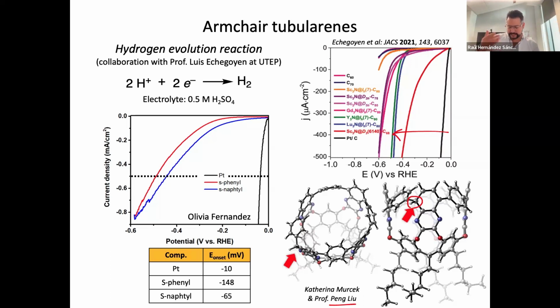There were hints in the literature that you could do this with CPPs. However, asking some of the leading scientists in CPP chemistry, they told us that one of the things that happens is you see a 1,2 shift in the aromatic system, and the system is done, right? All of that strain energy, as opposed to being funneled into making a hydrogen bond by addition of electrons, you actually funnel it into a 1,2 shift, and there's no more strain. Not here, because it's aided by this scaffold that keeps the structure in that configuration. Cool. So we think of this as a new design tool for HER, and we're still exploring some of these features with other compounds that we're making as we speak.